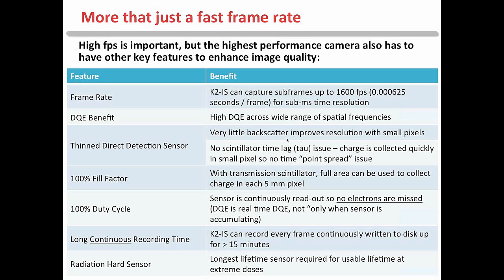Not only the high frame rate, but the high DQE, and lots of importance in terms of how the detector is built, in terms of fill factor and duty cycle. And I think the bottom one's a noteworthy one. You need to have something that's radiation hard, right? Because you're bringing high energy electrons into the camera, which can damage the camera. But frankly, we've had this for 18 months or so, and we're still on the same sensor. If you anneal it every once in a while, it seems to help recover it, and we've been able to use the same sensor for quite some time. So that's a good thing.